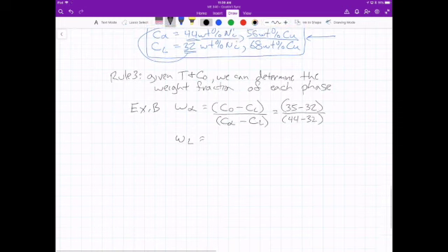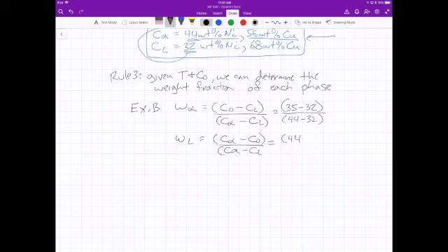So I do the same thing for liquid. I have to flip them, right? I have to use the line that goes from the solid to my point to calculate the amount of liquid. Okay. That's the lever rule. So instead I start with C alpha, my solid concentration, subtract my C naught, over the entire length of the line, which would be C alpha minus C liquid. Right. So I plug in those numbers. I get 44 is my alpha, 35 is my C naught, over the entire length of the line, 44 minus 32. Okay. And also remember, weight fraction of liquid plus weight fraction of solid must always equal 100%. Therefore, you really only have to calculate one of these, and then you can always just subtract from 100 to get the other one.